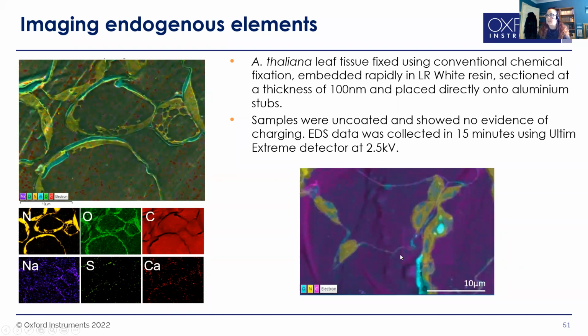And we're getting some really nice signals. Again, you can clearly see the nitrogen signals and this really beautiful nitrogen map highlighting those cells. And we're starting to get calcium. We're not really activating calcium particularly well at 2.5 kV, so that's why the signal's a bit patchy, but we are still getting some of the signals through.